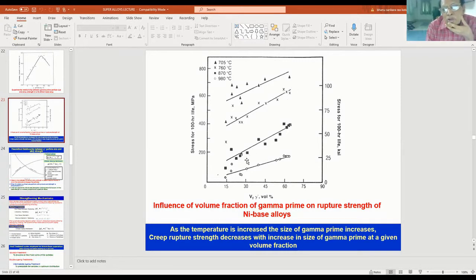If you go to 870, you look at that, it is coming down. If you go to 980 degrees centigrade, still it is much lower. So contribution to strength, creep strength, depends upon the application temperature. That is what we would like. So as the temperature is increased, the size of gamma prime increases, and creep rupture strength decreases with increase in size of gamma prime at a given volume fraction.